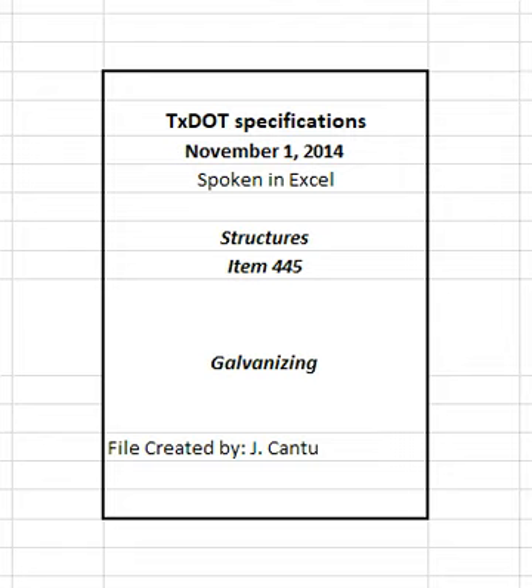3.2 Painting galvanized materials. Provide a paint system if painting is specified on galvanized materials in accordance with DMS 8102, paint systems for galvanized steel. Follow all manufacturer instructions for surface preparation and application, including the following. 3.2.1 Surface preparation. Do not water quench or chromate quench galvanized surfaces to be painted. Prepare the surface in accordance with ASTM D6386. Apply coating within 12 hours of cleaning. Reclean the surface if more than 12 hours elapse before initial painting.